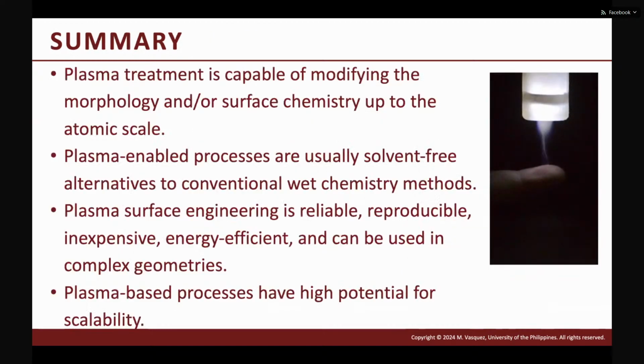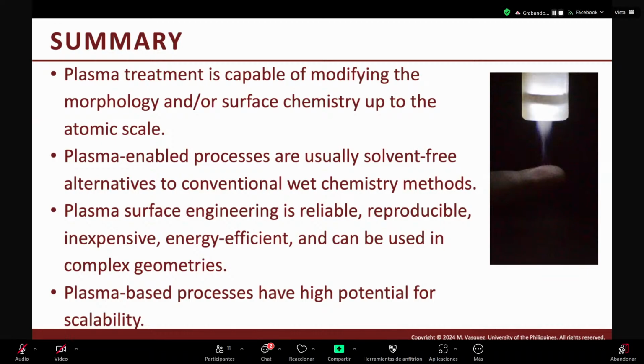So to summarize, plasma treatment is capable of modifying surfaces physically or chemically. And the good thing about plasma is that you can use solvent-free methods beyond conventional wet chemistry. From our experience, plasma surface engineering is reliable, reproducible, mostly inexpensive, maybe energy efficient, and can process complex geometries. So we also see that plasma-based processes, especially atmospheric pressure processes, have high potential for scalability.